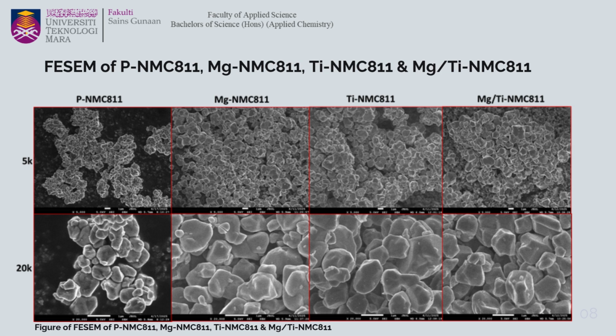For titanium-doped NMC, we observe particles loosely agglomerated with visible gaps between grains. The structure is more open, which could improve ion accessibility, and this loose assembly could be due to the lattice strain introduced by titanium ions. And for the co-doped NMC, it shows more agglomerated particles with partial fusion between grains.